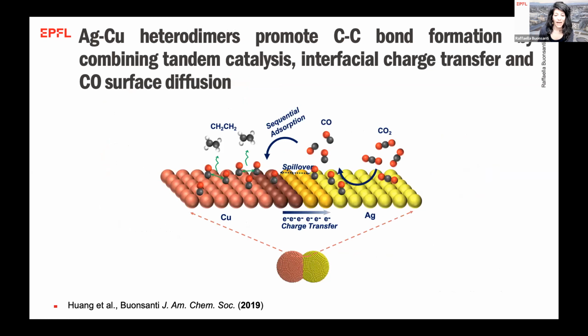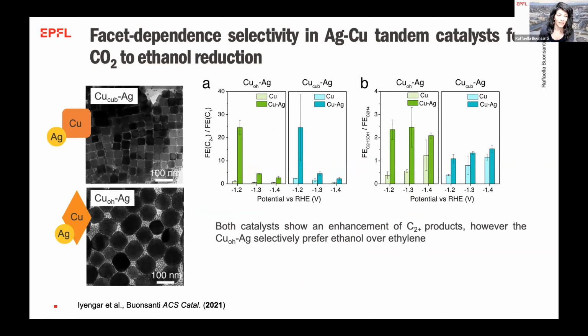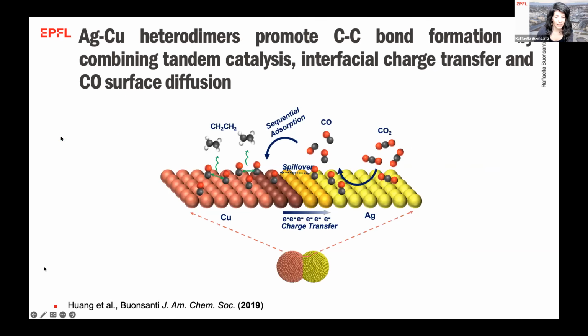And therefore, here the presence of this interface becomes crucial to enhance the CC coupling, so this electronic effect arising at the interface because of the charge transfer is crucial to enhance CC coupling along with the tandem effect. I also want to point out that also in this case, the facet that is exposed matters tremendously, because as we start to combine in a similar fashion copper cubes and copper octahedra, instead of spheres, what we observe